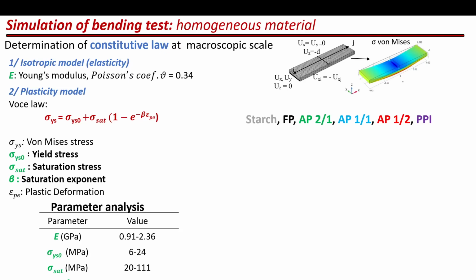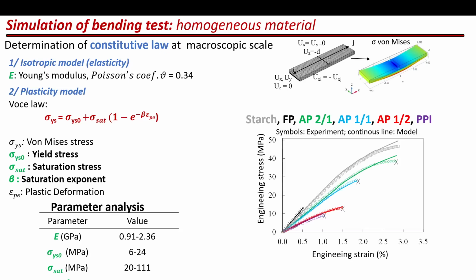So the behavior of this law is sketched on the right part. This is the parameter window that we used for simulations, for Young's modulus but also the three other parameters related to the plasticity behavior. And here is the predicted behavior of all samples, including the composites, the flour, and the starch phase as well, where we could see that we achieve a pretty good agreement between the experimental and the numerical behavior.